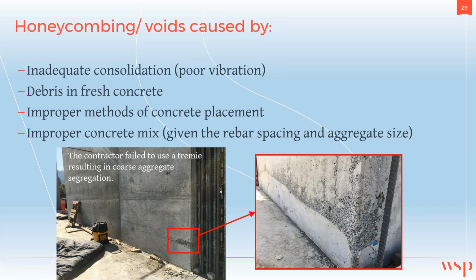As a result of that, the coarse aggregates ended up segregating during the free fall, and the contractor did not have a vibrator long enough to reach the bottom of the form, and that's why they ended up with honeycombing here at the bottom.